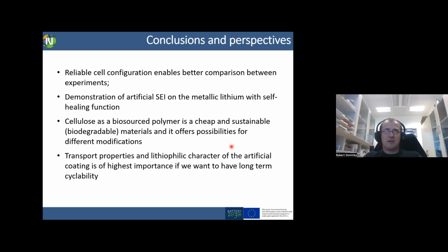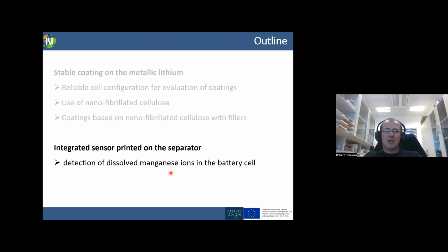I hope I showed you that this is a reasonably simple methodology that we have developed, using a renewable and abundant natural polymer with some tricks to stabilize everything. We have already achieved quite significant improvements, but of course some transport properties might still hinder the usage, although we have also tested these protective layers with current densities of between 5 and 10 milliamp per square centimeter, and still some energy can be obtained in combination with NMC cathodes. And now I will move to the second part of my talk,